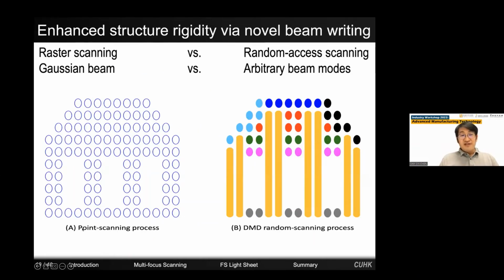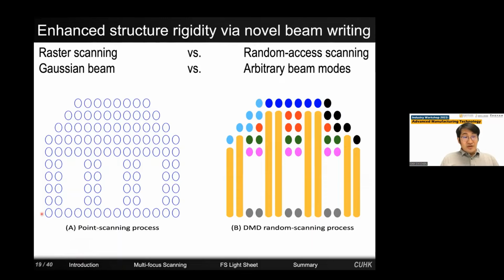Okay, so here we briefly compare the conventional process and our random access scanning process using this 2D example. In the conventional raster scanning process, the laser has to be scanned layer by layer. So even if you have empty spots, you have to scan through them and just turn off the shutter. In our process, shown on the right, each color represents one exposure, so we can expose multiple points simultaneously. We can build these pillars through a different beam mode, for example, the Bessel beam. As a result, we don't really need to go to these empty spaces. Based on this principle, we increase the fabrication speed by around 2 orders of magnitude compared with the point scanning process.